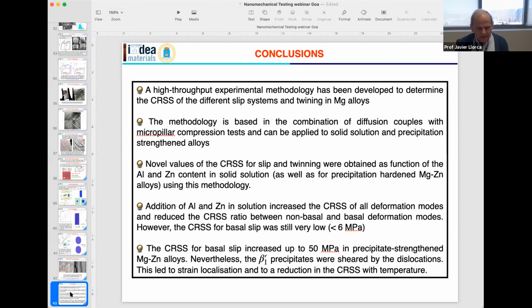What is more important besides the quantitative results is that this methodology can be easily expanded to obtain the critical resolved shear stress of any alloy, and it's a high throughput methodology that provides very accurate results of the critical resolved shear stress at a much lower cost than the typical technique that involves casting single crystals and doing mechanical tests in single crystals. And that's all, and I just thank you for your attention.